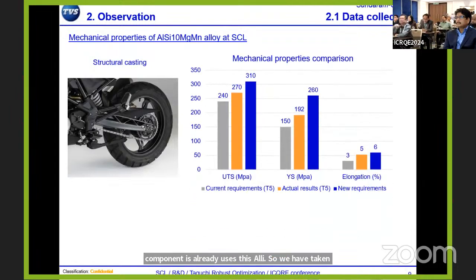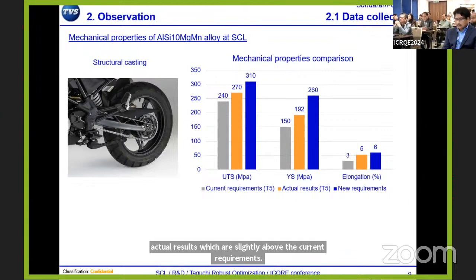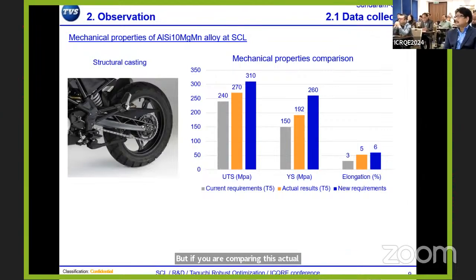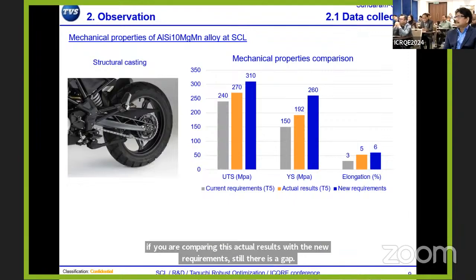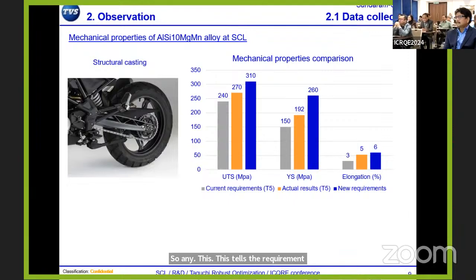If you see the mechanical properties comparison, this is the requirement specified by the customer, which is highlighted in the gray bars. The actual results are slightly above the current requirements. But if you compare these actual results with the new requirements, there is still a gap. So this tells the requirement of the T6 heat treatment process.